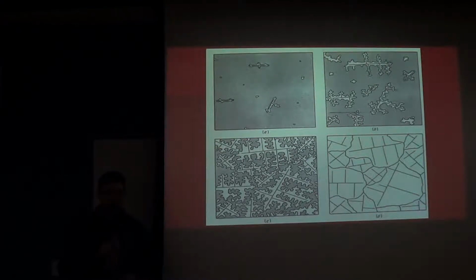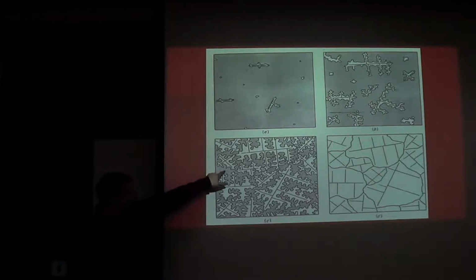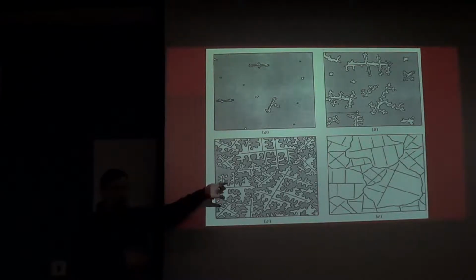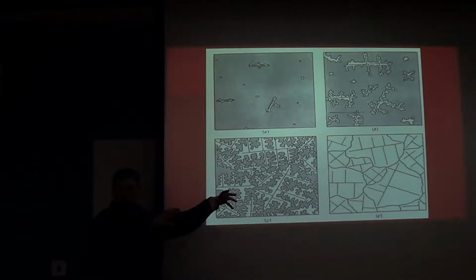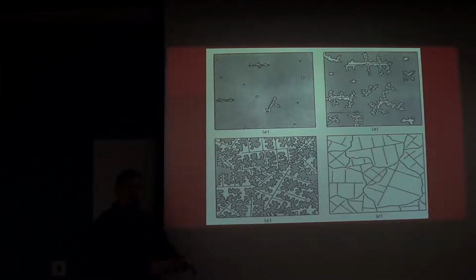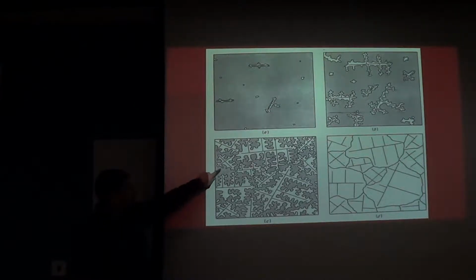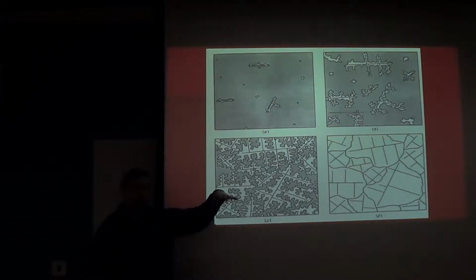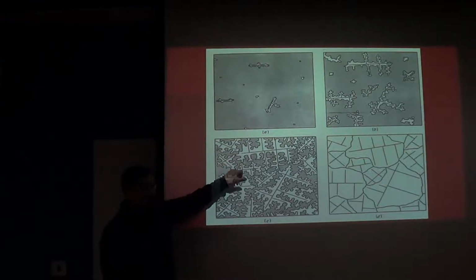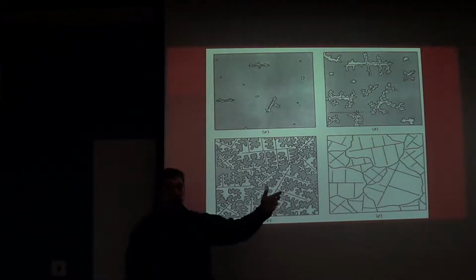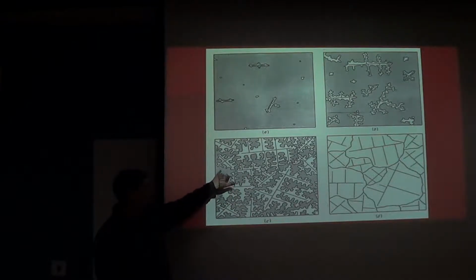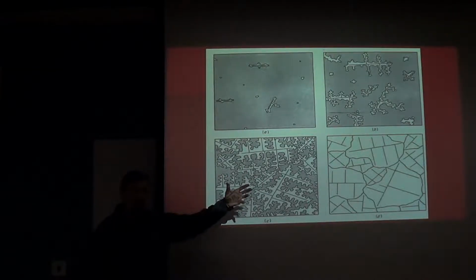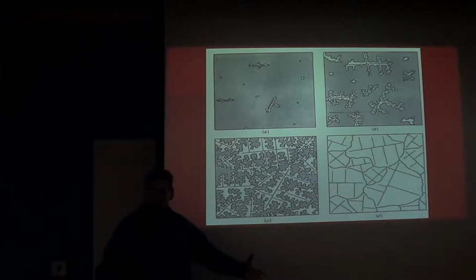You also gotta be careful with the really high carbon stuff, because if you get it too hot, you can have incipient melting, because you've got really high solute in those interdendritic regions. Right here. So just exactly what we were talking about before. On the macro level, carbon is pushed to the last metal to solidify, but the same thing happens on the micro level. So this region here is going to have a lower melting temperature than this region here. So if in heating you get to a point where this area starts to melt, and then you go to forge that, it's going to tear, crack, crumble, right?